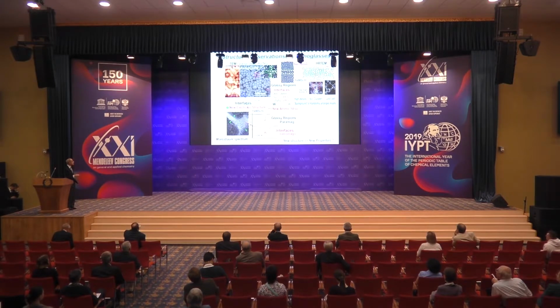But not only that, we get new atomic structures in these interfaces, we also get new electronic structures. And this is what we can see here. This is a nanoglass made out of iron 90, scandium 10. And this is the Mössbauer spectrum of the iron 90 scandium 10 glassy region. It's a single-line spectrum. This is the same spectrum you see when you take a bulk piece of iron 90 scandium 10. The new and surprising effect came when we looked at the interfaces. When we look at the interfaces, the Mössbauer spectrum all of a sudden is very different and has 6 lines. And 6 lines indicate the interfaces are ferromagnetic.